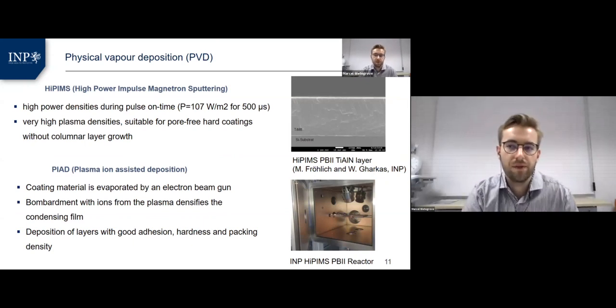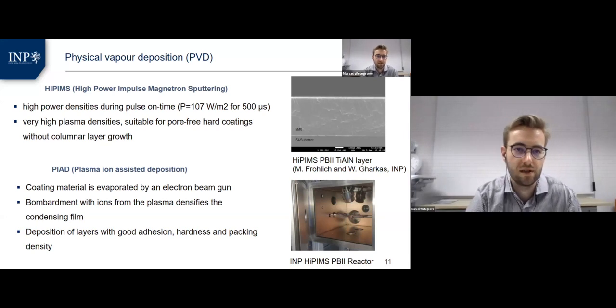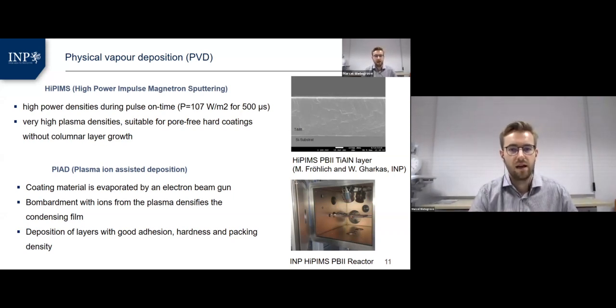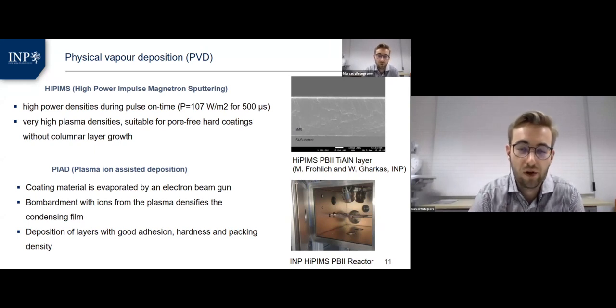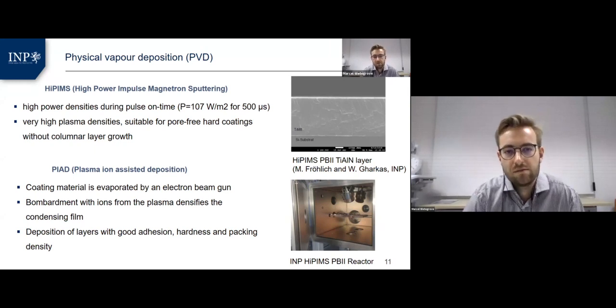When it comes to deposition methods, we mainly use plasma-assisted physical vapor deposition methods, such as high-power impulse magnetron sputtering and plasma ion-assisted deposition. These methods have in common high bombardment with plasma at a high energy density, achieving very compact layers that are very well suited to achieve pore-free hard coatings that show good hardness and adhesion, and that avoid columnar layer growth, which could